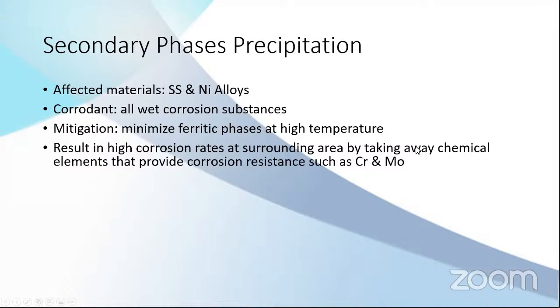The concept is similar. The secondary phase is what we normally call intermetallic phase. So the metals diffuse into each other and then become intermetallic. And the problem is that the ones that diffuse and react with each other are the ones that give corrosion resistance, for example, the chromium and molybdenum. And when they react with each other, they cannot protect the materials. So the area surrounding this secondary phase will have very fast corrosion.